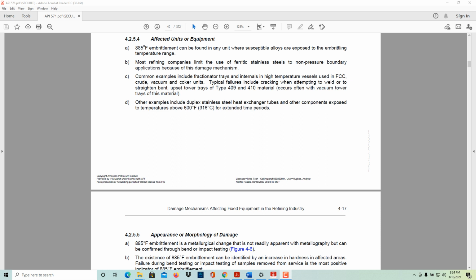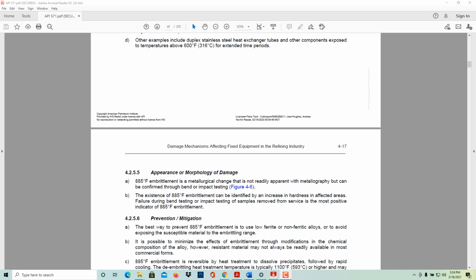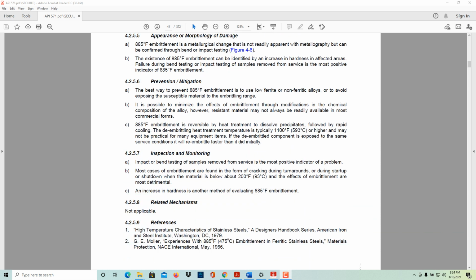Other examples include duplex stainless steel heat exchanger tubes, or other components exposed to temperatures above 600 F for extended periods of time. Morphology or appearance. 885 embrittlement is a metallurgical change that is not readily apparent with metallography, but can be confirmed through bend or impact testing. The existence of 885 embrittlement can be identified by an increase in hardness in affected areas. Failure during bend or impact testing of samples removed from service is the most positive indicator of 885 embrittlement.